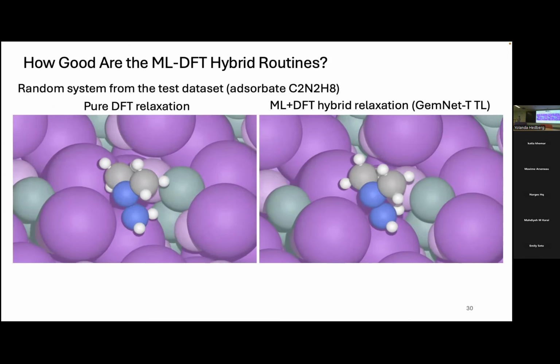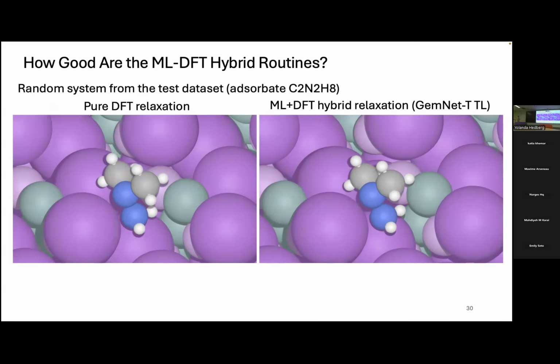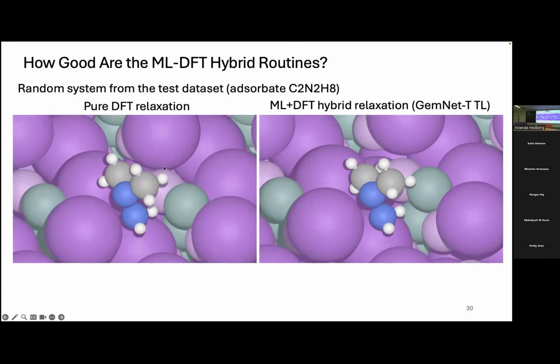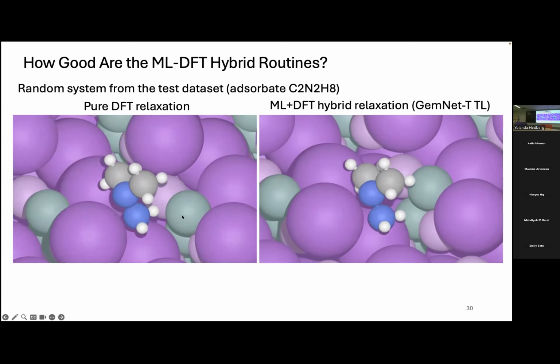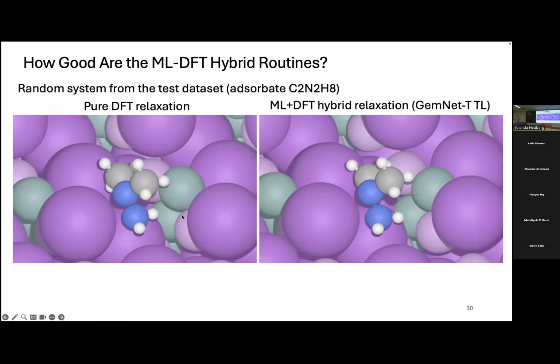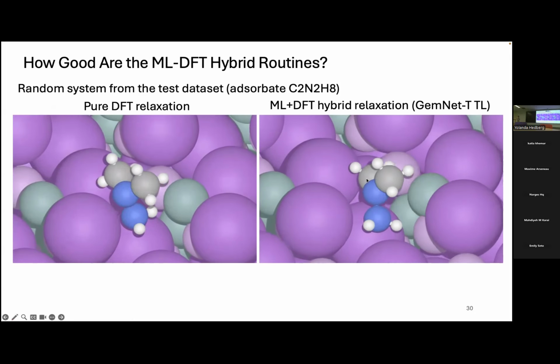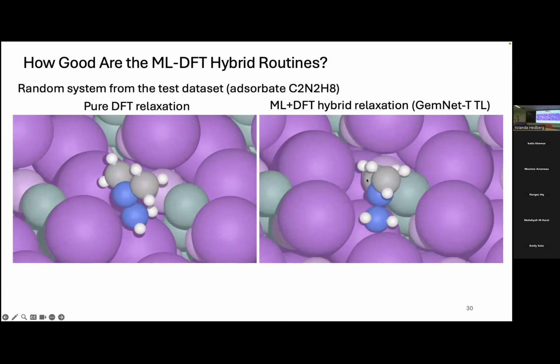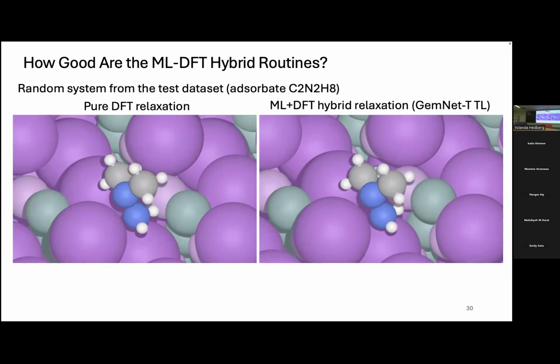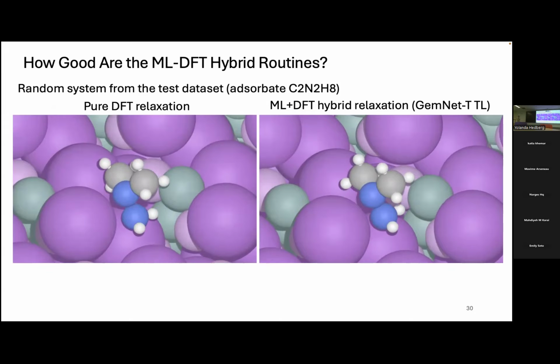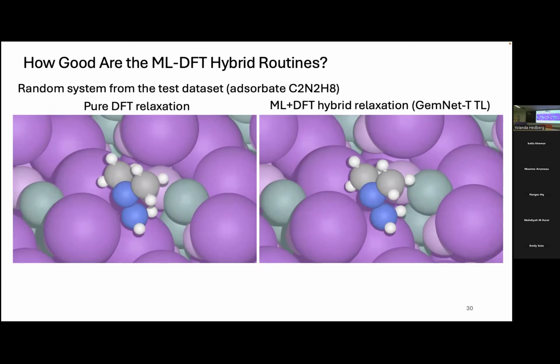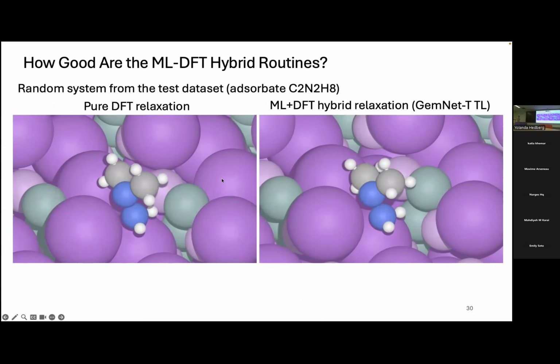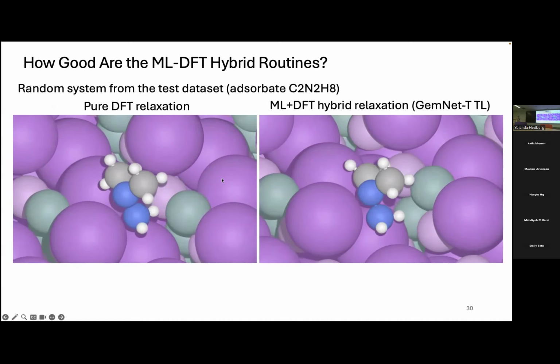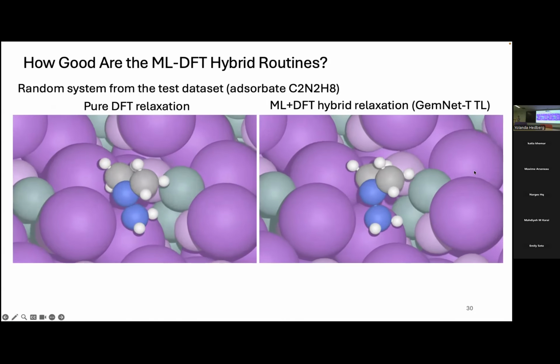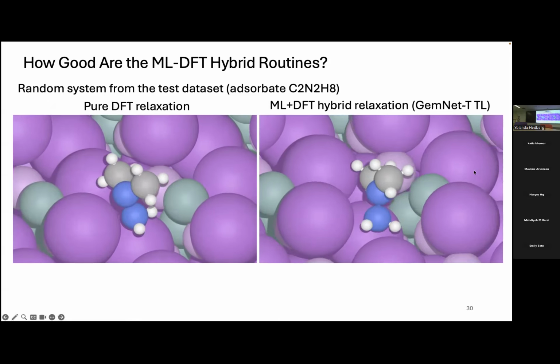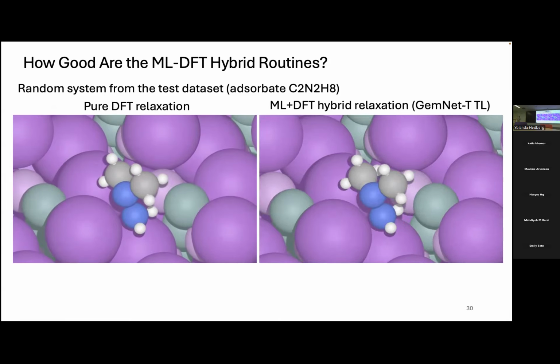One example is if you're going to study a very difficult adsorption energy simulation. The left-hand side is using a pure DFT relaxation. The atom is moving very slowly on the surface, and each time frame is a very expensive calculation. On the right-hand side, we have this hybrid relaxation scheme. Because the machine learning can explore much faster, even into slightly distorted geometries, it makes the discovery of the relaxed state much faster than purely using DFT relaxation. So you can almost say that on the right-hand side, you can reach the ground truth 10 times faster than the left-hand side, and you are also guaranteeing the final result about this adsorption energy is fully correct.